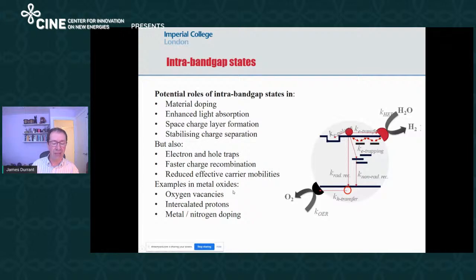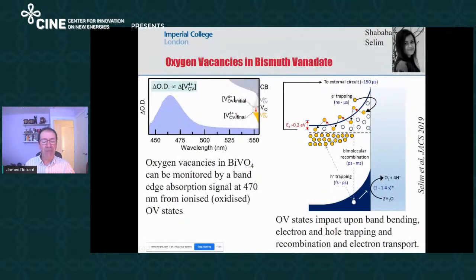Many oxides tend to be substoichiometric in oxygen, which is why most oxides are N-type. Now, we found that many of these oxygen vacancies can be tracked optically by an optical absorbance, which is probably an electroabsorbance signal near the optical band gap. And so, for example, Shababa has been studying in detail the kinetics of charge trapping and charge transport in these oxygen vacancies in bismuth vanadate.